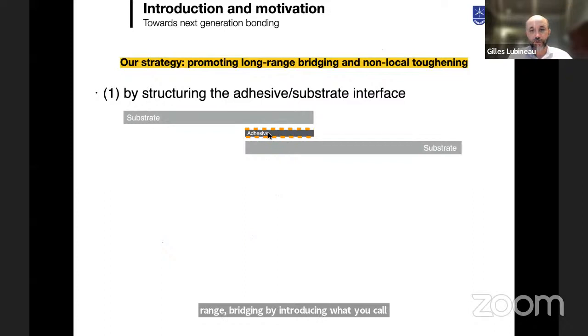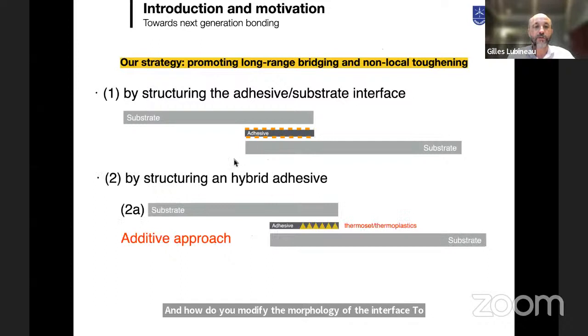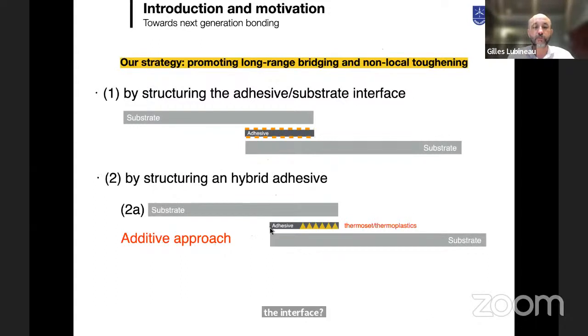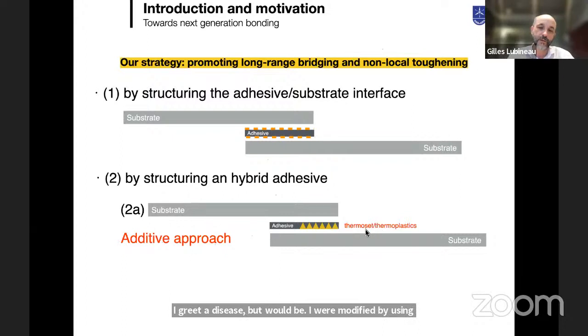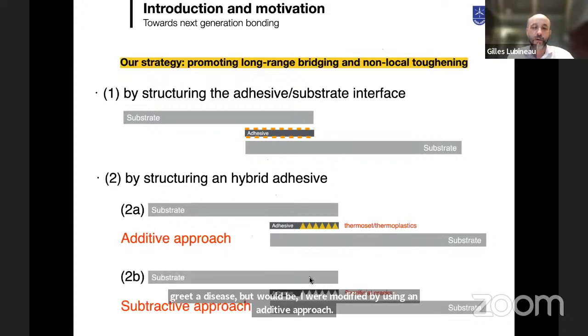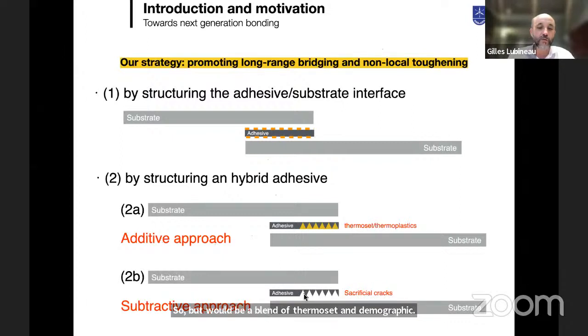That means you have the adhesive, you have the substrate, and how do you modify the morphology of the interface to make sure that you will modify the response of the interface? Then the second strategy will be introducing a hybrid adhesive. If I look at the adhesive here, we are going to make a hybrid adhesive that will be modified either by using an additive approach, a blend of thermoset and thermoplastic, or by using a subtractive approach. That means just introducing what we call sacrificial cracks, pre-designed defects in the adhesive, and how this is going to modify the response of the joint.